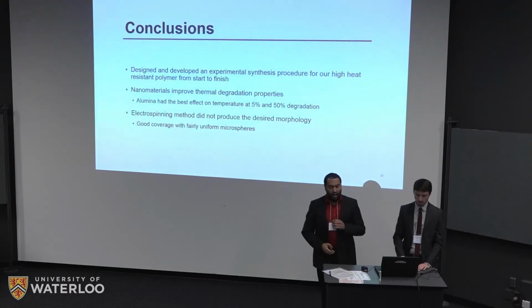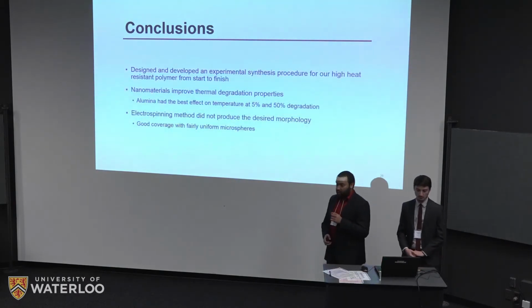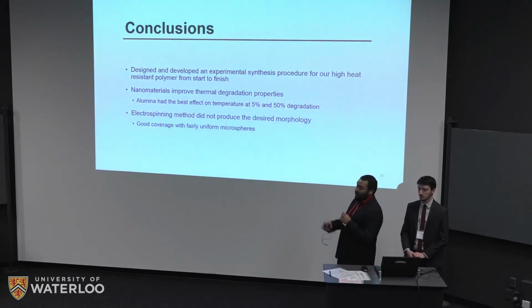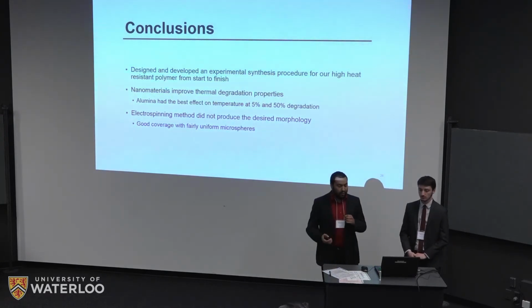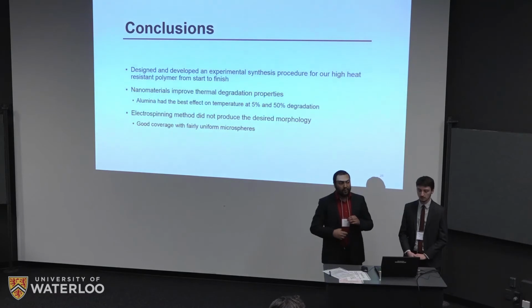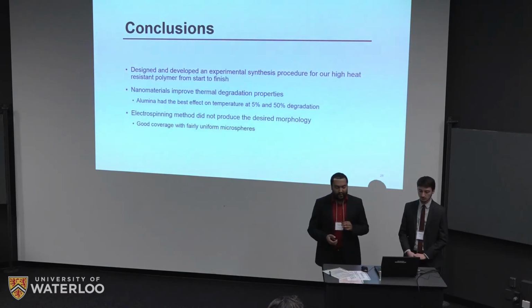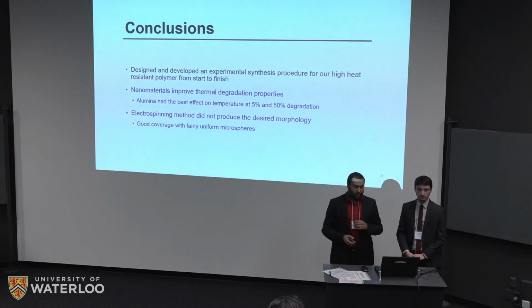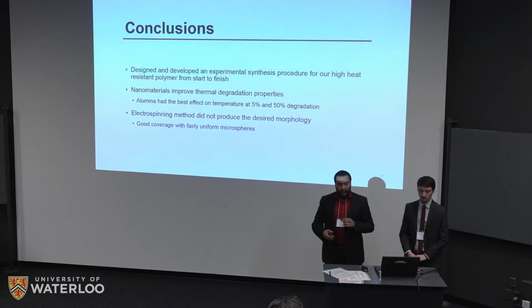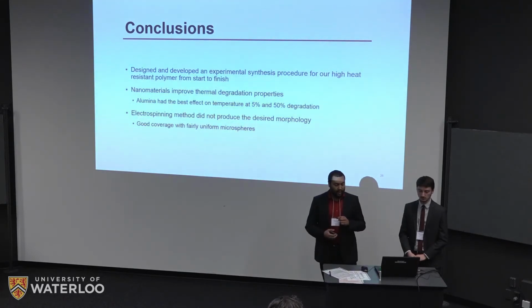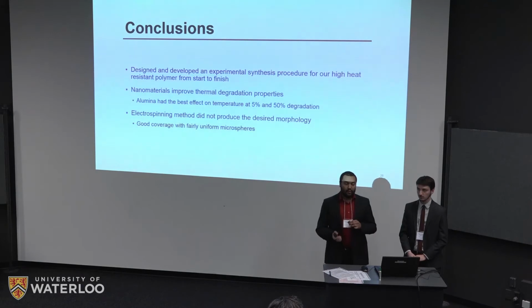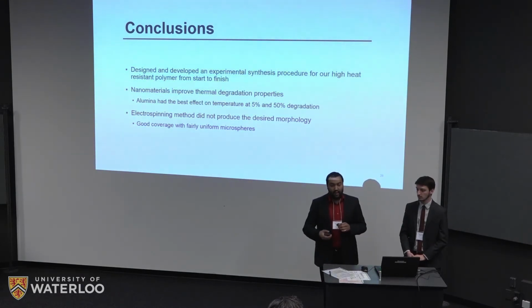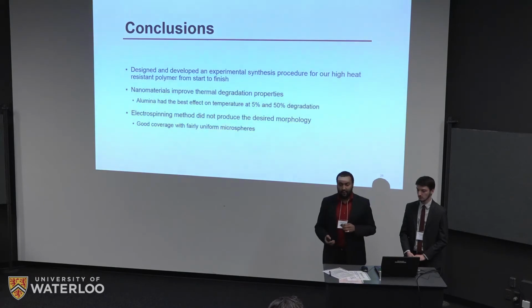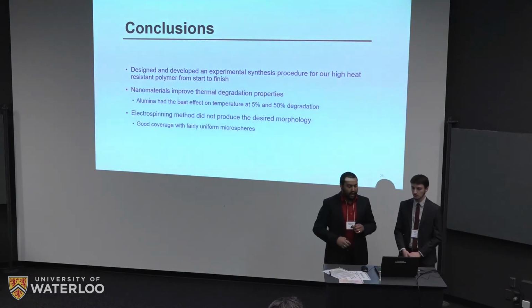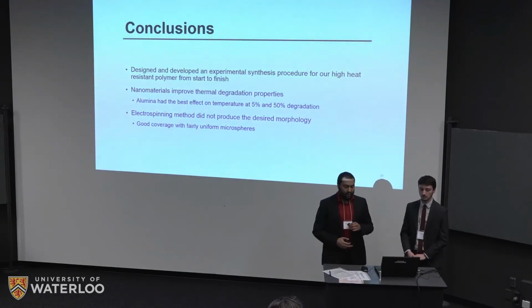So some of the big conclusions that we can draw from this project. Firstly, we designed and developed our own experimental synthesis procedure from start to finish to synthesize this high heat resistant polymer. We were able to improve the thermal degradation properties with nanomaterials, most specifically with alumina. This had the best effect at 5% and 50% thermal degradation. And so we would like to look into that further.